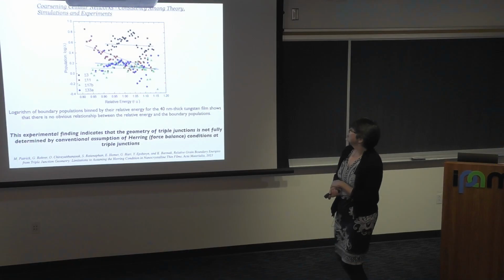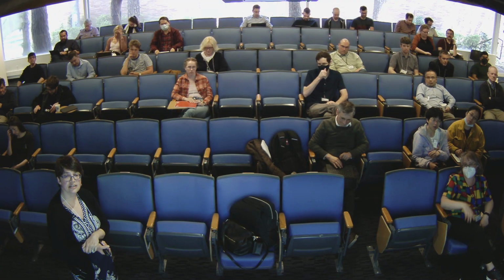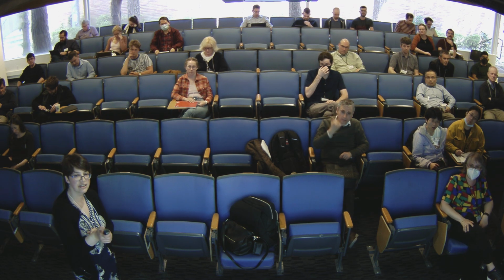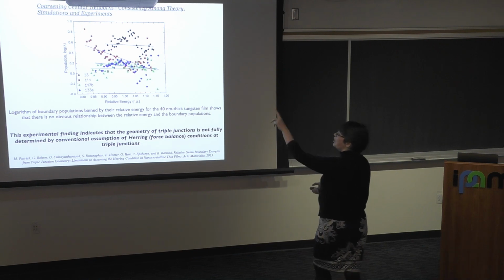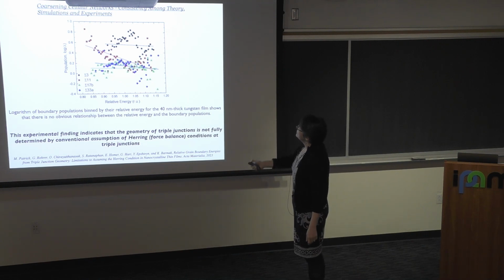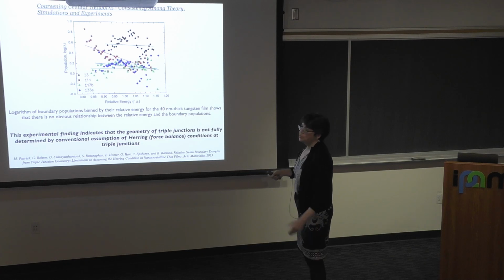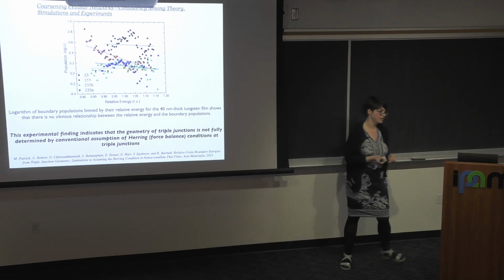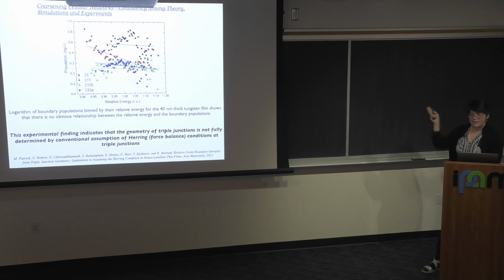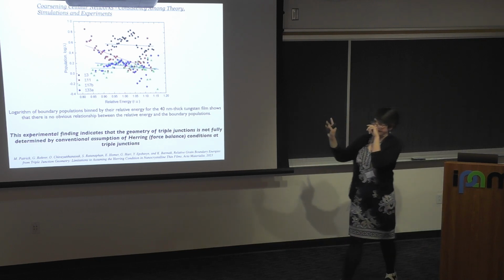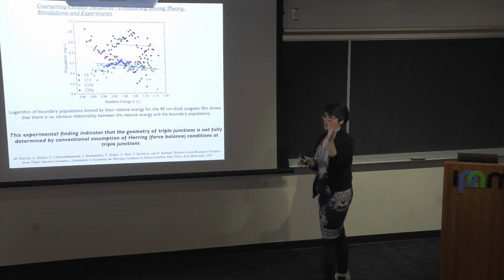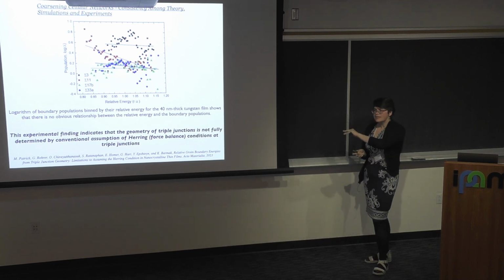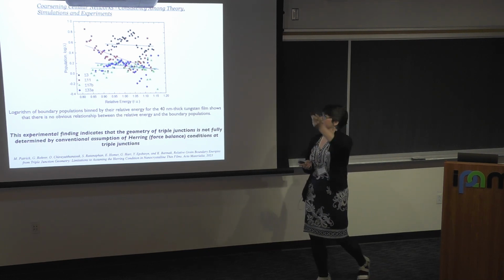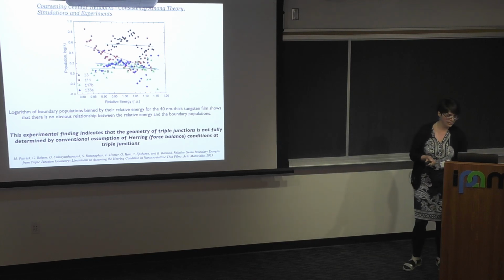Yes? What are the different markers here on the experimental data? Well, I think different grain boundaries, like sigma 3, sigma 11, and population. And from these, you see that there is no inverse correlations. And similar results, so this is tungsten, and similar results we discovered from aluminum as deposited sample and also after they annealed. So that was very interesting.